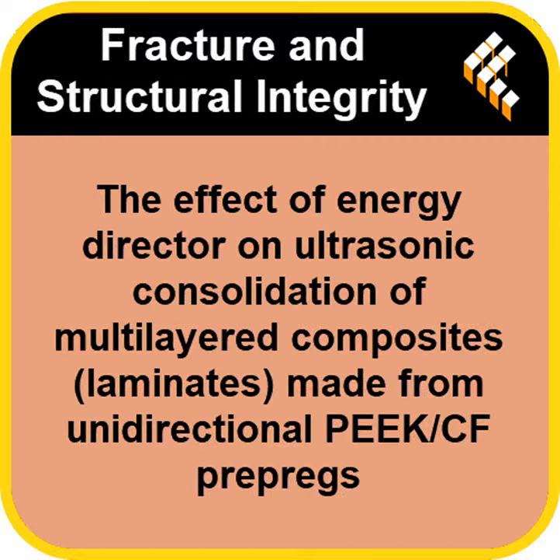How does this optimized UC method stack up against the traditional super slow methods? Well, it's competitive, but it's not yet superior in pure strength. UC offers these huge speed advantages, but the ILSS values they achieved are still about 40% lower than what you get from traditional thermoforming, where the material has hours to diffuse perfectly. Right. But they are matching up really well against other cutting-edge rapid techniques.